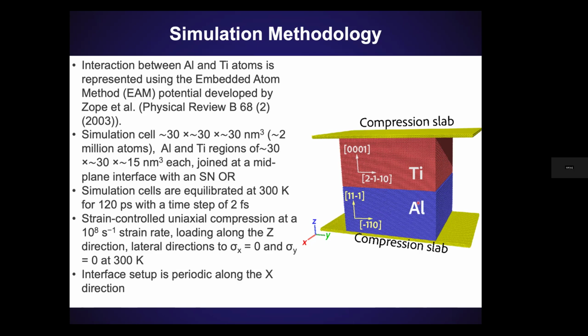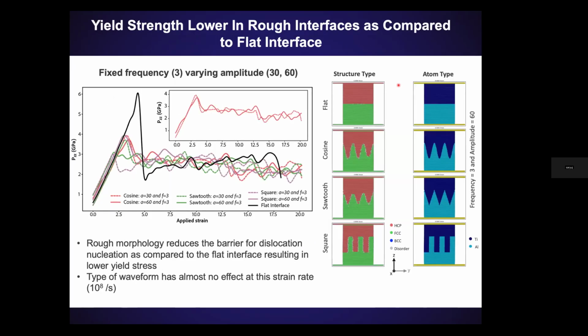We're going to have our two materials, flat and different wavy interfaces. We're going to apply uniaxial stress, so just compress it from top and bottom, measure the stress strain response, along with quantifying some dislocation densities as a function of that interface shape. And really, the end goal is if we could make our material stronger by changing that interface shape, that's a win for us. Or maybe the answer is you can't do anything because that interface shape doesn't matter.